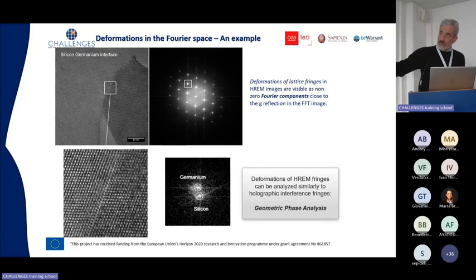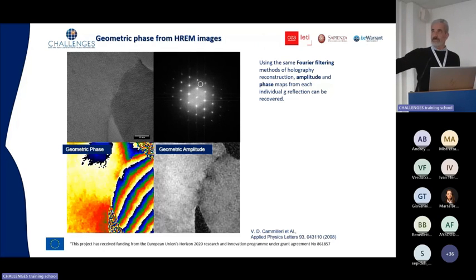You see here an enlargement of this interface from silicon and silicon germanium. And if you enlarge the spots here, you'll find that it is composed of two spots, one corresponding to the silicon lattice and the other to the silicon germanium. By performing the same Fourier analysis, by filtering the pattern, we can obtain, by inverse Fourier transforming, a phase analysis of these materials by taking the silicon as a reference.